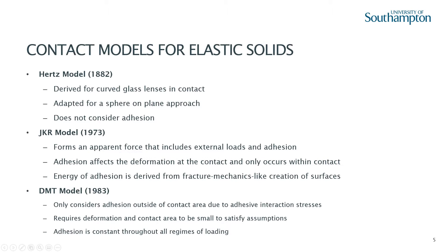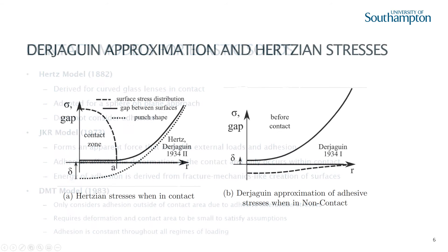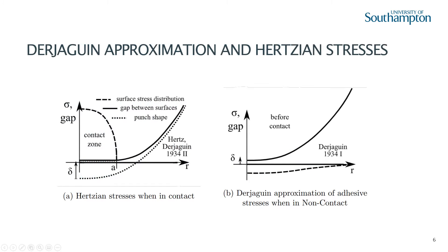The first of the three models considered was the Hertz model. First derived in 1882 in order to calculate the deformation of curved glass lenses, the Hertz model only seeks to satisfy the boundary conditions of the mechanical problem and does not consider adhesion between the two bodies. It is valid for elastic solids across a large range of scales and levels of stiffness.